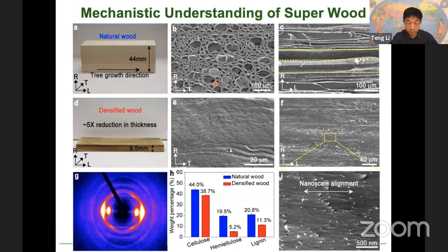You can see that all these cell walls collapsed. And after the collapse, they form these intertwining finger-like structures, really hand in hand. And not only that, even the small pits on the surface of the cell wall disappear. And we maintain the alignment of the cellulose nanofibers in the natural wood, it actually becomes even better. As you can see in this higher resolution image here, this is the nanoscale alignment of the cellulose fibers, also evident here.